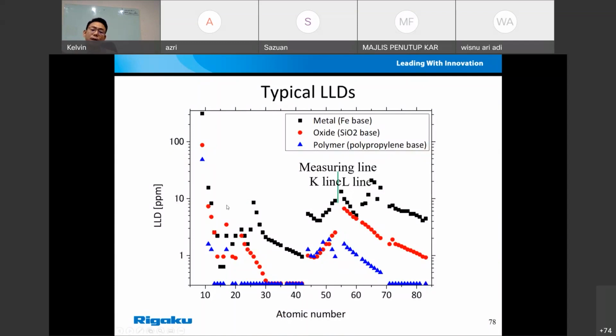As you can see in here, in the polymer, you can detect up to like 1 ppm. Where you have an iron-based sample, the minimum amount is what you call 100 ppm or even 200 ppm and so on. So this is one of the very important factors for how low your lower limit of detection, which is what LLD stands for, can go.